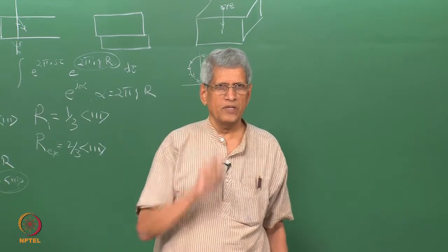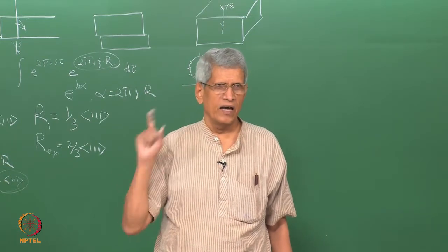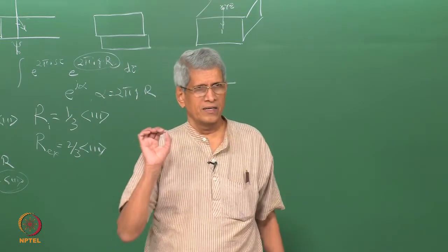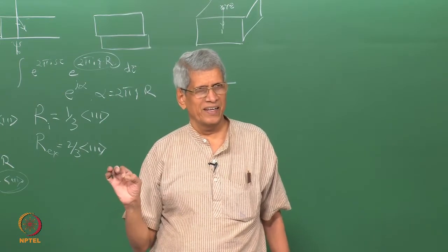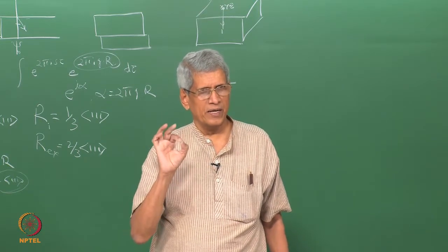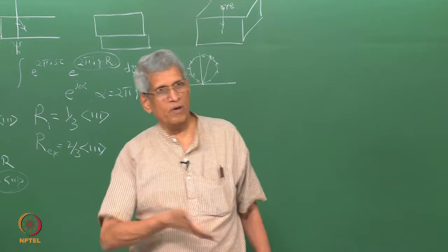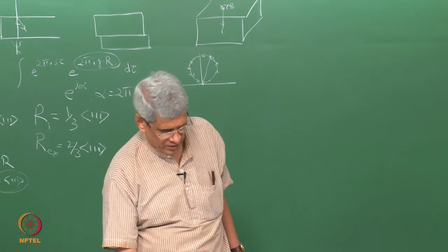All those symmetry elements which are lost, they appear as defects in the ordered lattice. That is, translational symmetry elements which are lost will appear as antiphase boundaries, and the rotational ones which are lost will appear as domain boundaries, and all of them, these are all planar faults, so they give rise to essentially a fringe contrast.